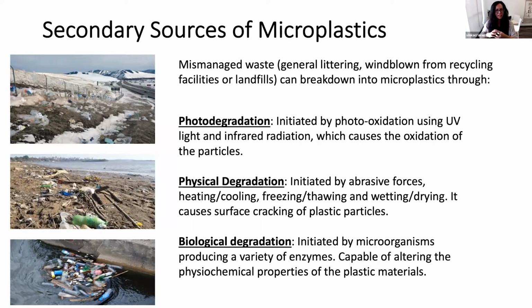Also the freezing and thawing process helps to create fractures, because the material contracts and then expands. That starts creating small fractures and increases the chances of breakage. And when you have these micro fractures in the plastic, you are increasing the surface area. So they give organisms more chances to start growing, forming biofilm, and selecting organisms that may be able to use some of this polymer as a carbon source or energy source.